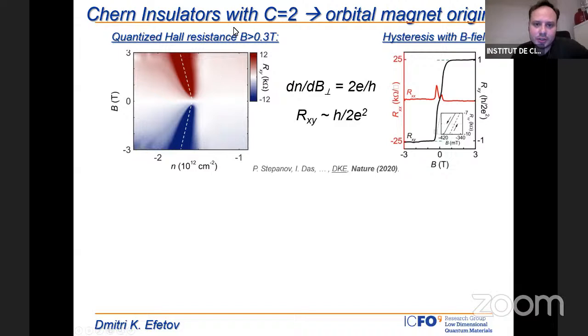We see Chern insulators, and how Chern insulators manifest themselves in our measurements is that we observe regions of quantized Hall resistance, quantized to h over e squared, and usually the exact quantization value depends on the integer filling of electrons per moiré site, which we choose. So we observe these Chern insulators with Chern number 1 originating from a filling factor of 3, we observe Chern number 2 from filling factor 2, and we observe Chern number 3 from filling factor 1.